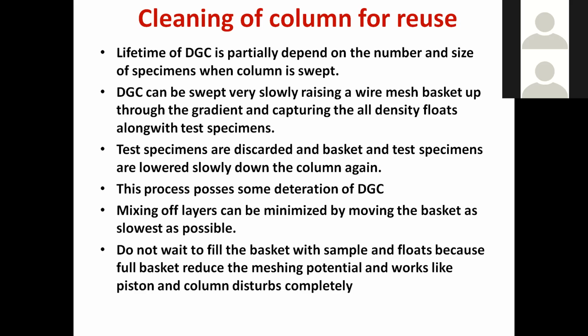So to bring the basket up for sweeping the column is also recommended to be done at very slow speed. This process poses some deterioration of the DGC, density gradient column. Even after maintaining all these precautions, when you lift the basket and lower the basket, there may be some deterioration in the column. It means up to some extent the column will deteriorate.